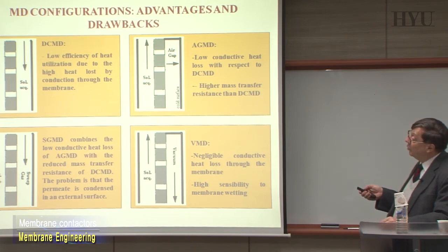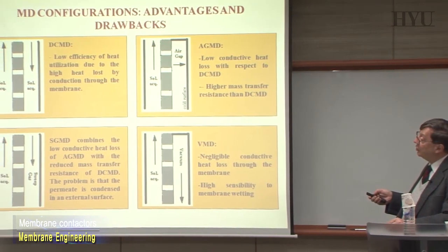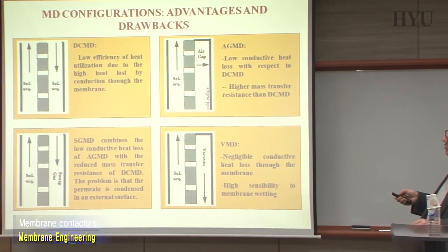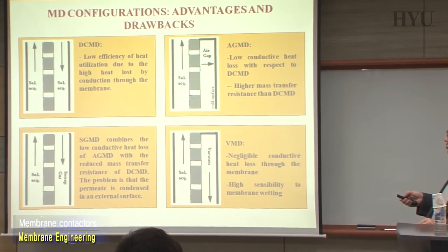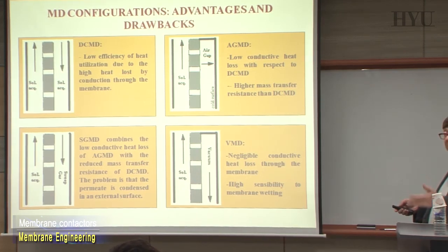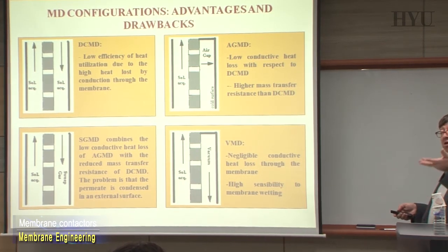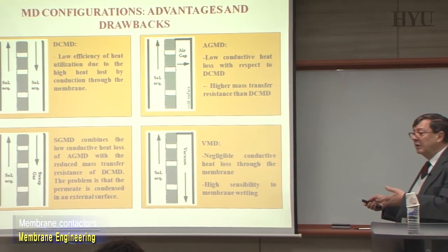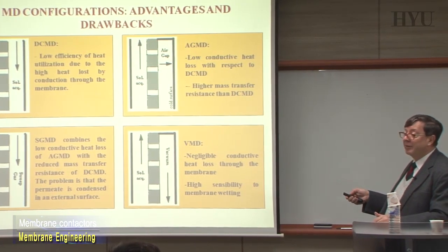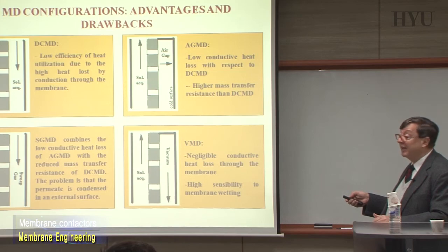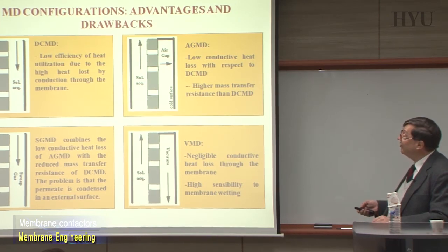For example, for what concerns direct contact membrane distillation, there's a situation where you have a low efficiency of heat utilization because we have a significant heat loss by conduction through the membrane. I mentioned it before. The heat that you are supplying to the system, instead of being utilized for the evaporation of the water, is utilized to warm up the polymer, and you create a temperature gradient across it, and that is heat lost. That can be about 40–50% of the energy.